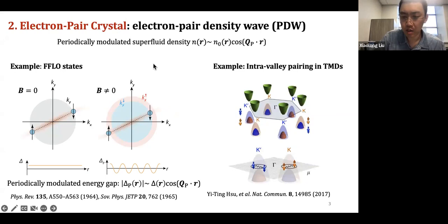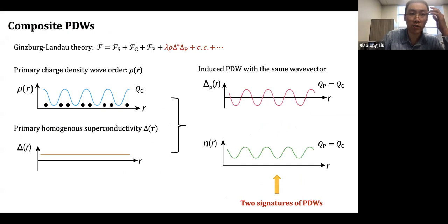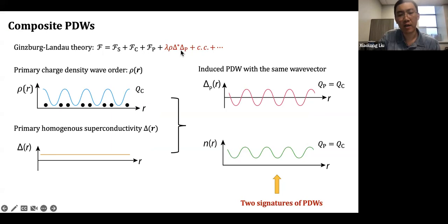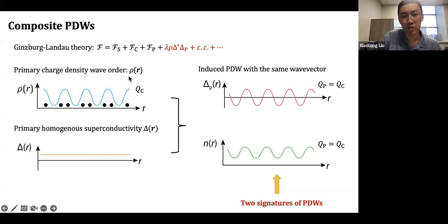What I talk about here are the fundamental paradigms — real fundamental orders that are primary in your material in a superconductor — but you can also have an induced pair density wave, which we call composite PDW. This comes from the very phenomenological Ginzburg-Landau theory: if you have a strong superconductor and also a co-existing charge order — say a charge density wave — Ginzburg-Landau theory tells you that you can effectively induce a PDW state. A non-zero ΔP will be preferred; you can induce a pair density wave by coupling uniform superconductivity with a charge density wave.